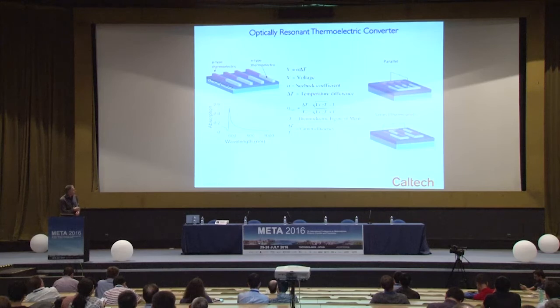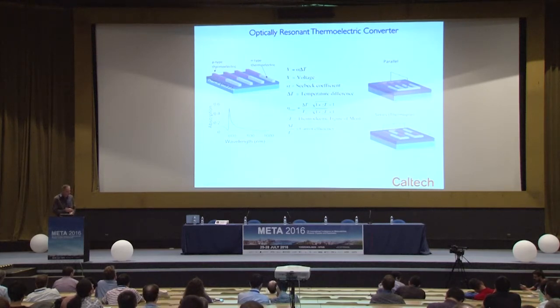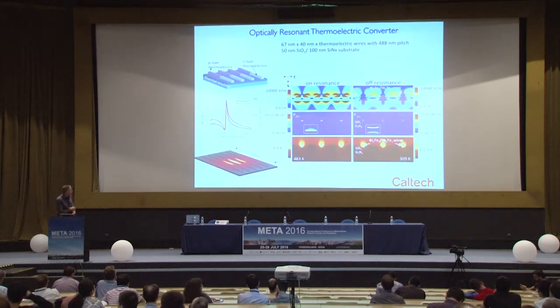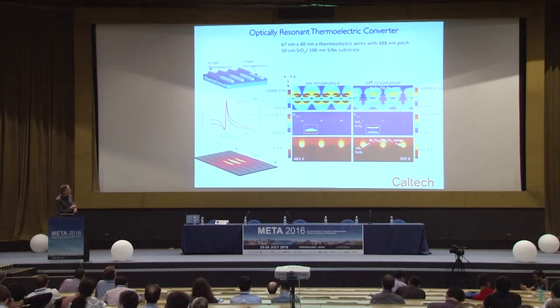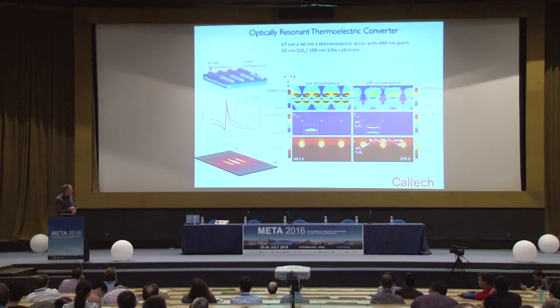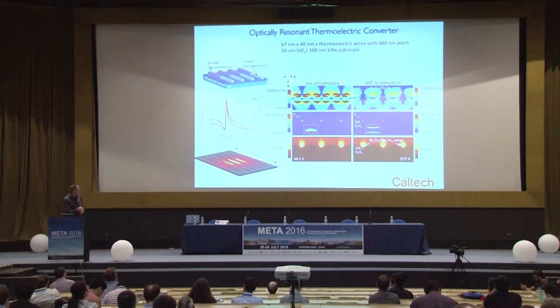So the Seebeck coefficient for bismuth antimony telluride, which is essential to the figure of merit, ZT, and the thermoelectric efficiency, is particularly high for this material. So we can see that, in fact, in the guided mode resonance structure, full wave simulations show a resonant temperature rise that is directly in accord with the resonant absorption. So essentially what we're able to do now is to make a material that serves as a thermoelectric detector, which is very, very broadband. This is unlike a semiconductor detector, which has a band gap cutoff. These detectors have essentially the same kind of sensitivity just because they're absorbing heat from the visible to the far infrared. And we can see this manifest as a localization and a temperature rise in which the resonant excitation of the thermoelectric wires itself leads to a change in temperature of the wires on and off resonance.